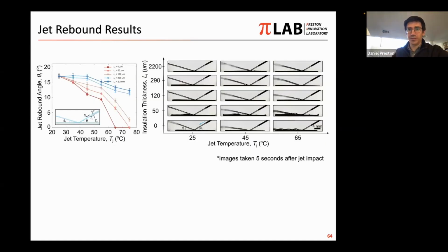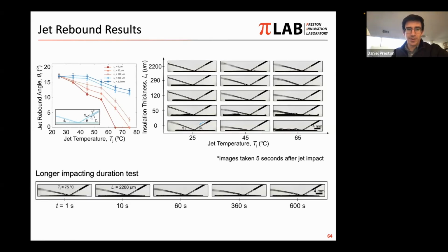We did this over a bunch of different temperatures, as well as insulation thicknesses, and found that the results agreed with our expectations. We also did it over time and found that even as we approach longer times, we don't lose this effect of maintaining superhydrophobicity with high temperature difference.